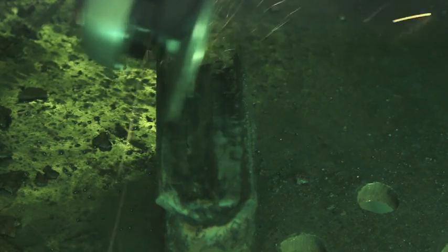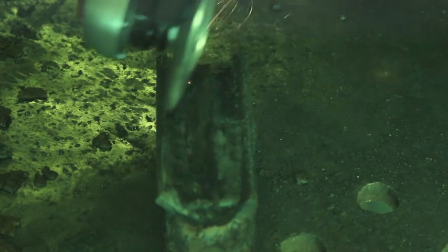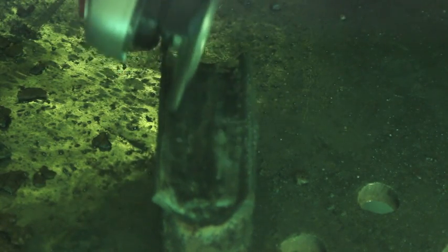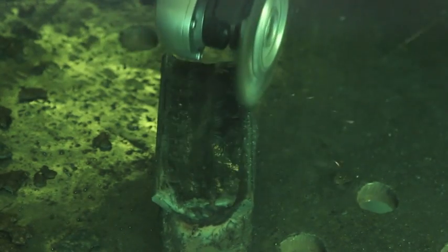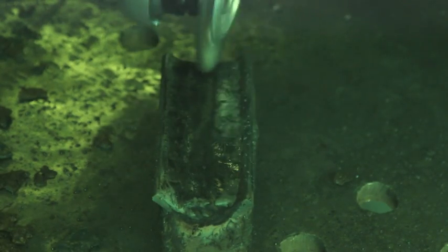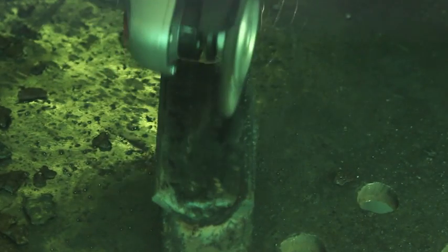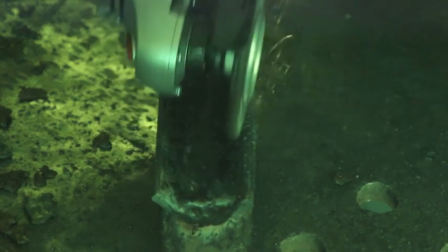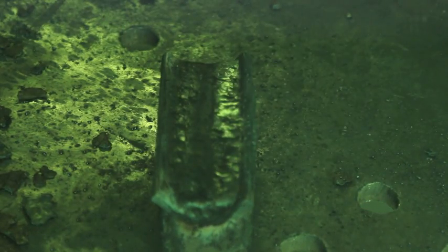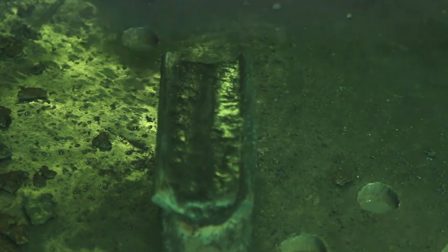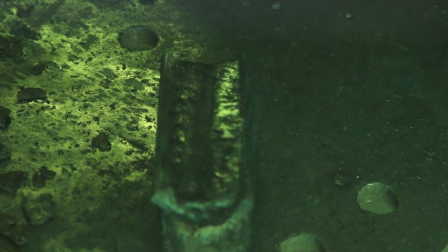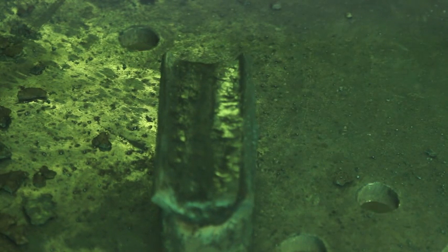So here are my recommendations to beginners. Number 1, clean your material thoroughly before you start. Number 2, don't skip steps. Start in the flat position and work your way up to vertical and horizontal. Do not start on vertical and horizontal. Number 3, make sure to visit the manufacturer's website, choose a wire speed and a voltage, set your machine, and do not change it. Work on your technique. If you're having problems, I guarantee you it's going to be your technique, especially at first. Try to resolve those technique issues before you change settings.